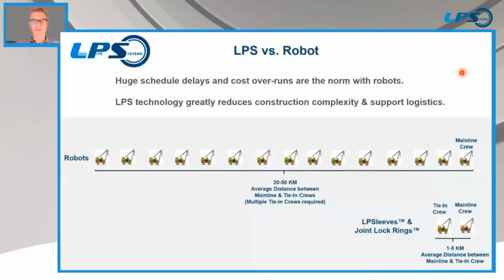So besides the quality concerns, one of the biggest issues with robots is the fact that the coating occurs after the welding is done. So the mainline crew will be welding along, moving down the line at a pace of a kilometer and a half a day. Robots simply can't keep up with that pace. So what ends up happening is tie-ins are left open. They'll construct maybe 500 meters to a kilometer. They'll leave in sections. They'll leave the ends of the pipe open so that the robot can get in and out behind them, coating all of those welded joints.